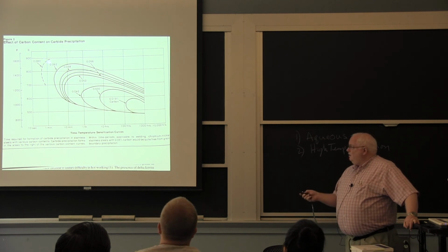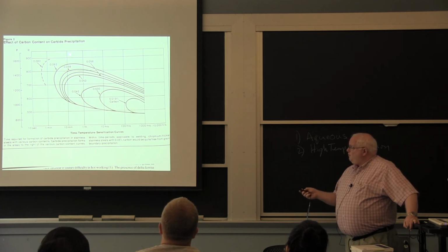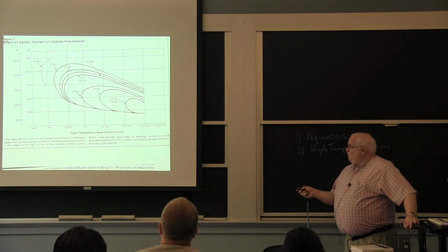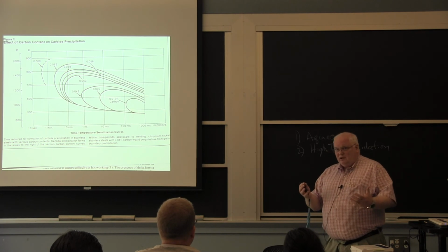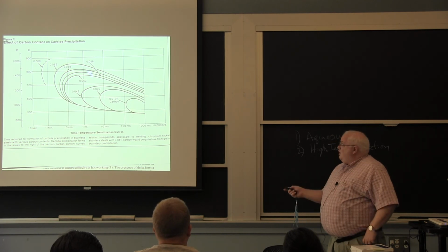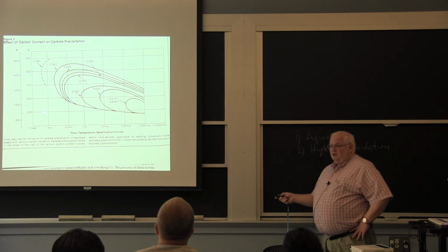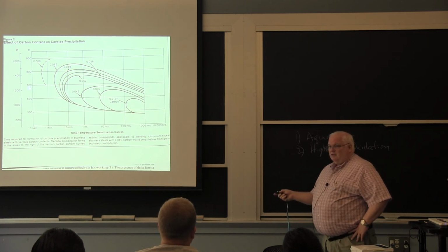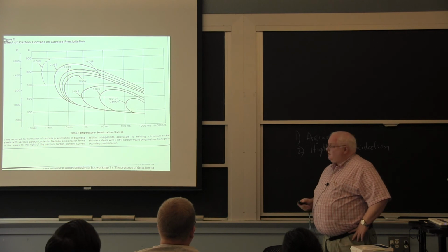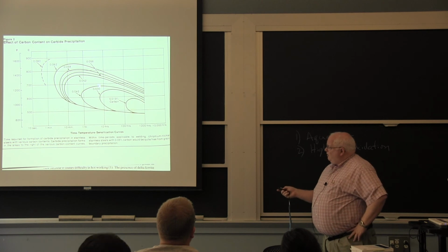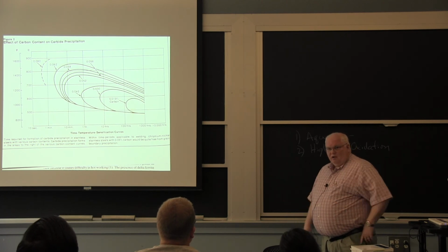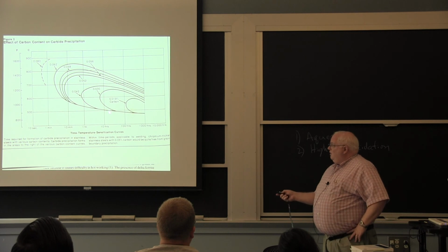So this is not that you don't have a problem, but what happens is if you go above 900 C, you can resolutionize those carbides, so you can heal the process. But above 900 C, the whole structural part could turn into a pretzel in the annealing furnace, and you have to quench it through this region within less than a minute, and so it's not very practical. So you have to be careful how you heat treat stainless steels. Unless you're 304L, boy, you got 10 hours here. You can weld them all day long, but you can't operate them between